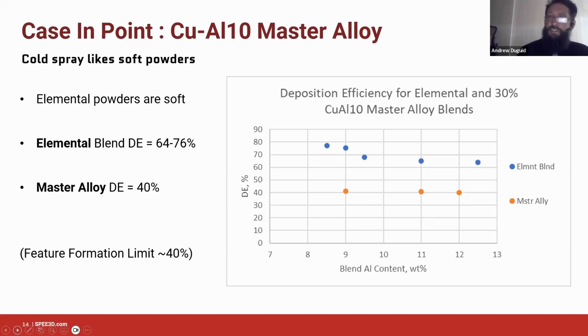And happily, what we found is that when you sprayed the elemental blend, we got a pretty substantial increase in deposition efficiency. It has a slight trend with the aluminium content and then seems to plateau from about 9.5% on. So that's that first stage. We selected our powders and we worked out how to get deposition. And then you can imagine doing this sweep across the aluminium content. What we're doing there is dialing in the aluminium content of the blend so that we wind up with the right amount of aluminium in the alloy at the end. And what this told us was we were way better off just sticking with an elemental blend. Okay, so we go on to the next slide.